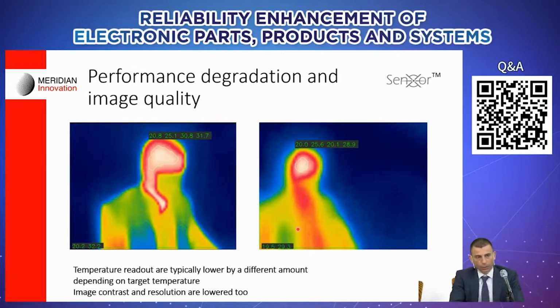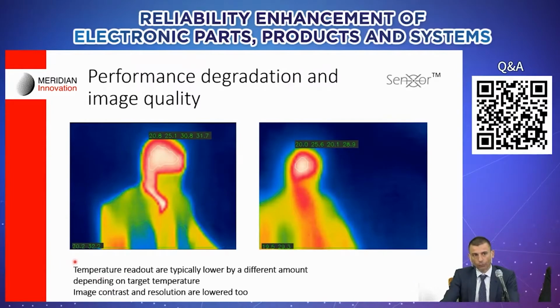So it is interesting to consider, in real-time operation, how would any of these potential degradation and failure mechanisms be manifested. And so here I compared two images in which one shows much sharper delineation of the subject, sharper contrast, and temperatures which are quite accurate for the setting, and considering the extreme of the scene and the segmented image.